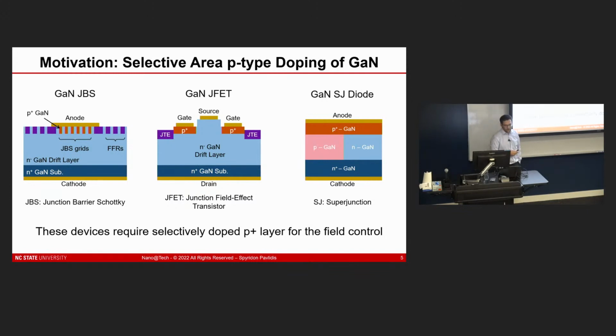And this has traditionally been a very big challenge for gallium nitride. One of the reasons is that, with silicon, one of the things we typically learn when we learn about semiconductor fabrication is that we can leverage something like diffusion doping, right? And so that's a very convenient way to get started. But with gallium nitride, that's not an option. These diffusion processes are very, very slow, so it's not practical to use them. You can also deteriorate the surface with the high temperatures that are needed. And then another very common practice, especially in cases like this, is etch and regrowth, and that etch and regrowth process can lead to damaged interfaces, which can also reduce the performance of your device. So we want to think about other ways of doing that, and I'm going to talk about two of those ways today.